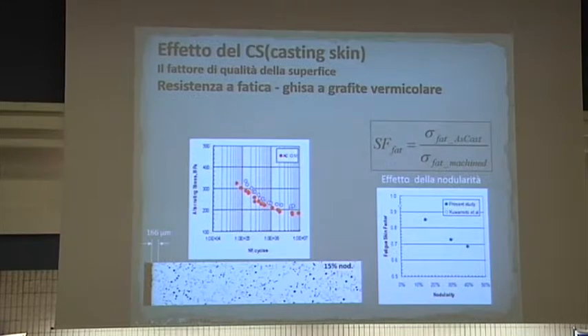And you can define in the same way a casting skin factor for fatigue. Same thing, ratio between as cast and machined, and you can see that it is affected by nodularity, and it's much lower than when the nodularity is less.